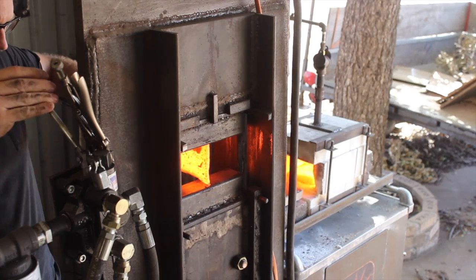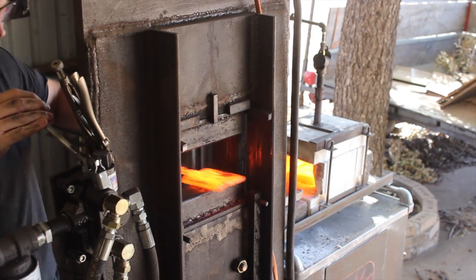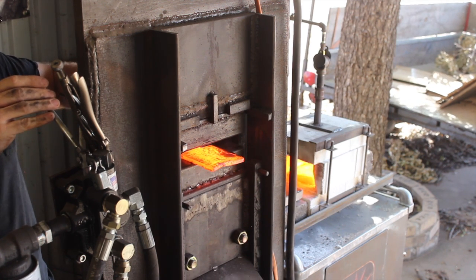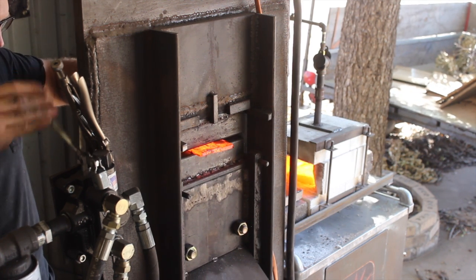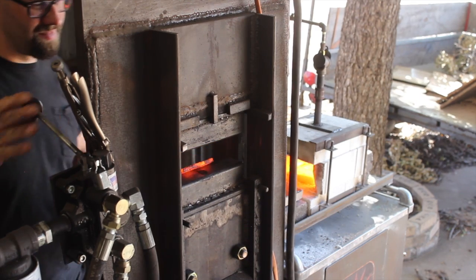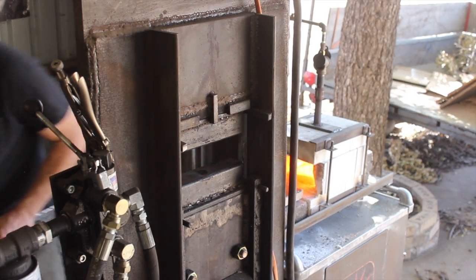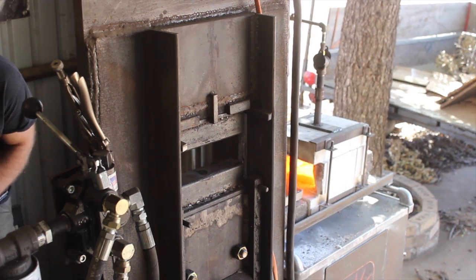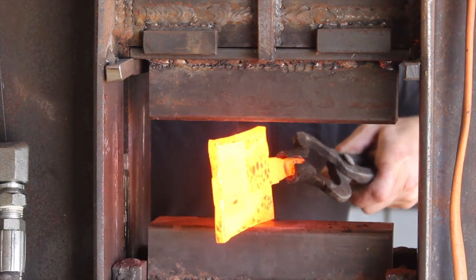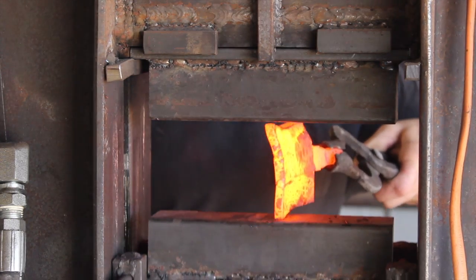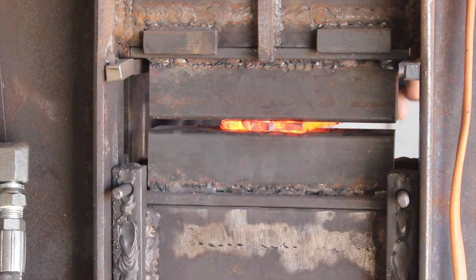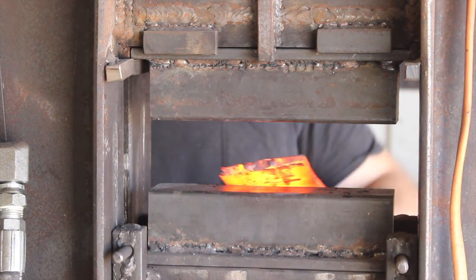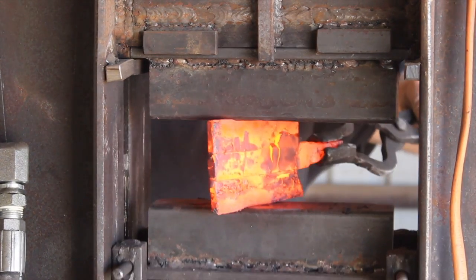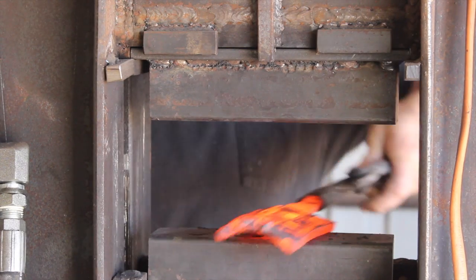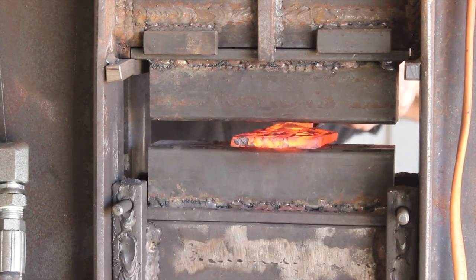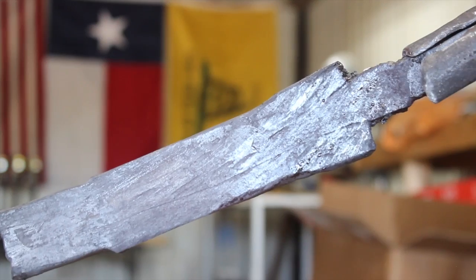So here's where things started to go a little bit south, as you can see. There's just not a way to get consistent, straight, even pressure on the forging press with such a narrow piece of steel. I think it was about 1/4 inch thick. So it just really didn't work that great. Of course, it was a great learning experience, and the next time I do something like this, I'll definitely use pieces of steel that are at least twice as thick, and also not as wide. I didn't need that wide of stock for the final ratio in the blade on the high carbon steel.